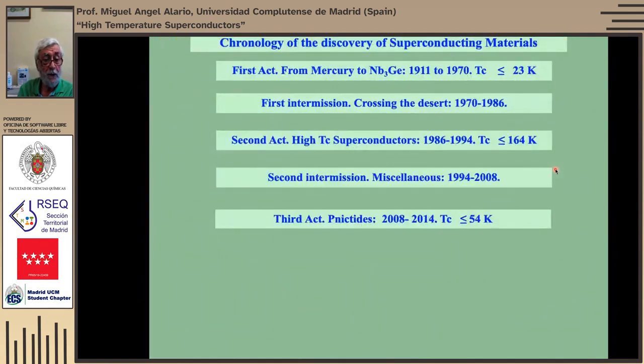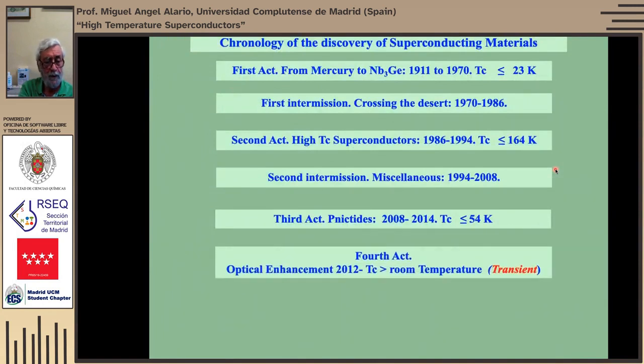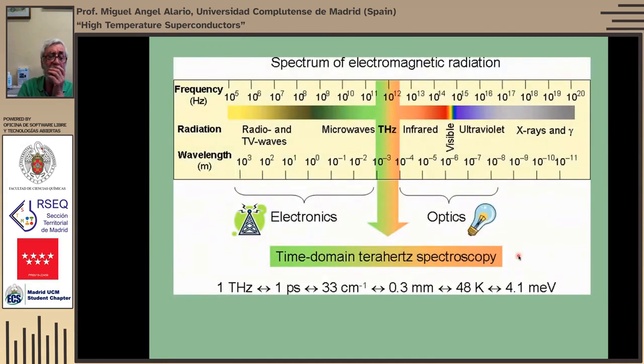So after the pnictides, we get to the fourth act, in which we will see optical enhancement of Tc up to room temperature, but in a transient mode. So for this, we have to recall the spectrum of electromagnetic radiation, which is the terahertz region, microwaves, infrared, visible. People here do not work with microwaves. But it's interesting, this terahertz spectroscopy, excuse me, because you can actually be very precise in making pulses of the terahertz region. And so 1 terahertz is about 4.1 milli-electron volt.